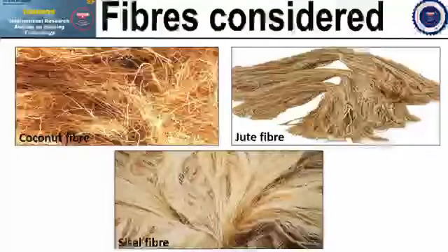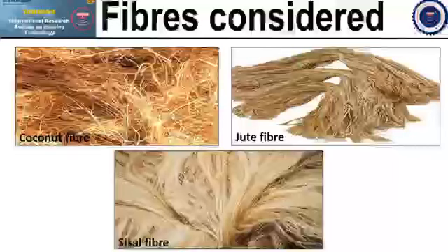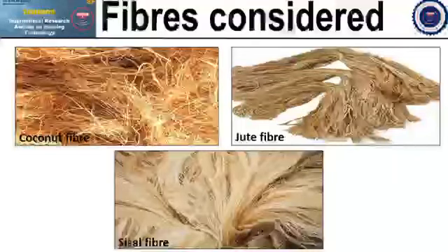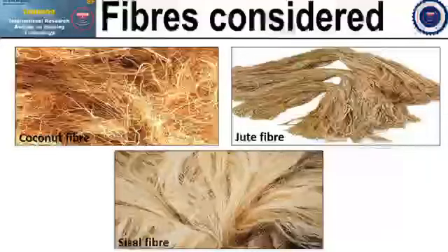Okay, therefore, my proposed research focuses on an experimental investigation on the mechanical properties of natural origin sustainable cellulosic fiber reinforced lightweight foam concrete. I did employ several natural plant fibers such as the coconut fiber, the jute fiber, as well as the sisal fiber with average length of 19 mm, which were mixed with lightweight foam concrete in varying weight fractions between 0.1 until 0.5. Okay, the results were also compared with the control samples without any fiber reinforcement, and the improvement in the mechanical properties by adding natural fibers was quantified.